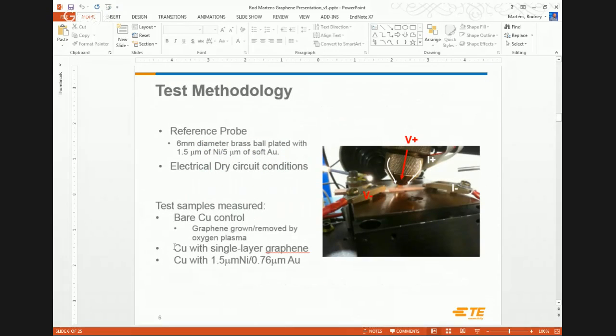All right, so it looks nice, but what I really care about is the electrical contact resistance. So if we have corrosion films on the surface, they're insulating, and we don't have good low-level, reliable electrical contact. So using an instrument in my lab, we're actually probing these surfaces and measuring the contact resistance right at the interface. We use a reference probe. So this was a 6mm diameter brass ball, plated with 1.5 microns of nickel and 5 microns of soft gold. So that's a nice, clean, soft surface that we use as a reference probe.